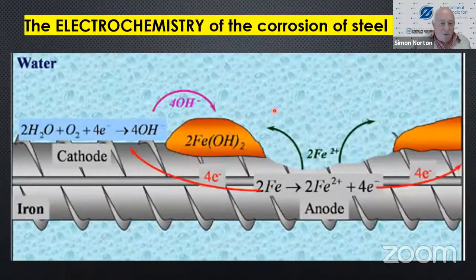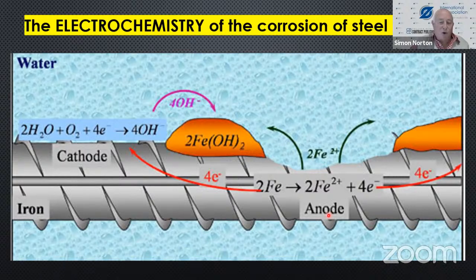Now, if you look at a piece of rebar in water, and this has got a generalized application to all steel. If you have a look over a rusted surface, before it rusts, there are scores and thousands of anodes and cathodes all over the surface. At the anode in water, the iron is oxidized to iron 2. It releases electrons. In this case, we have a balanced oxidation reaction.